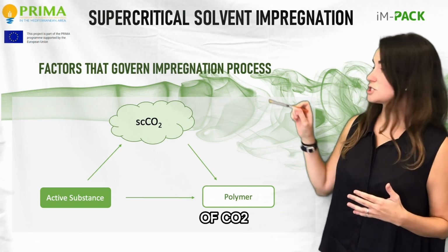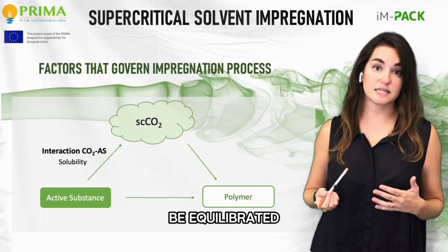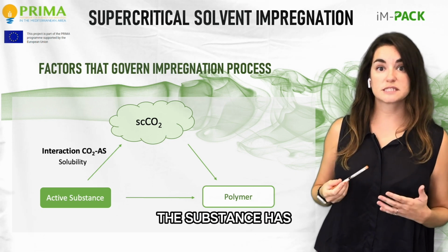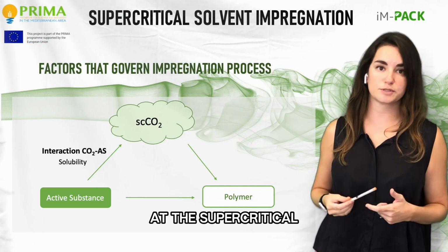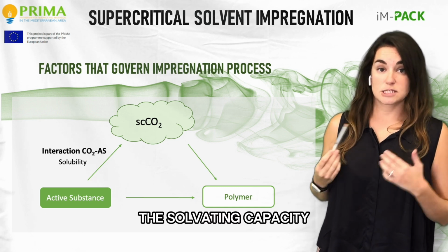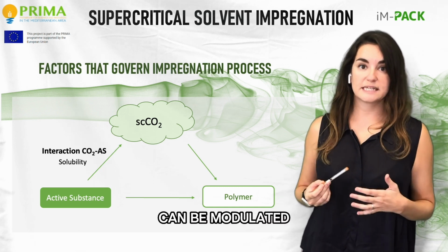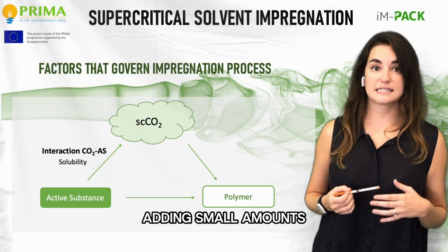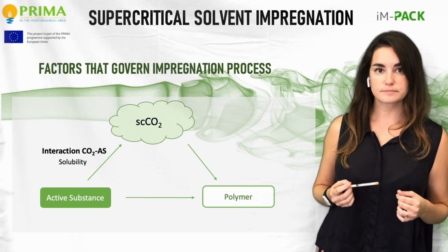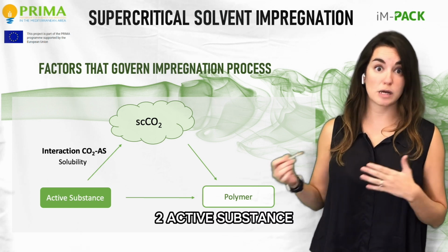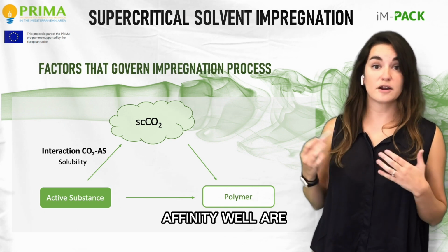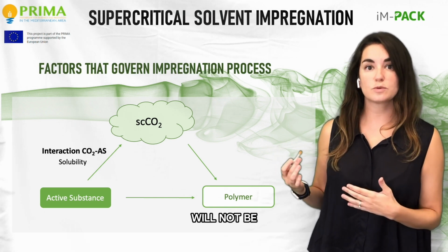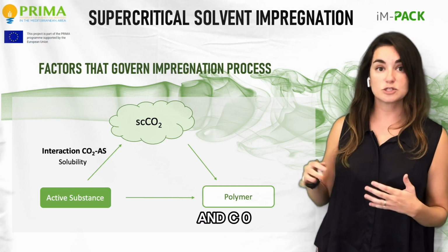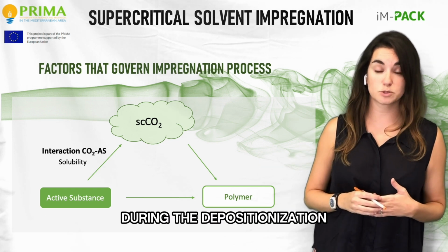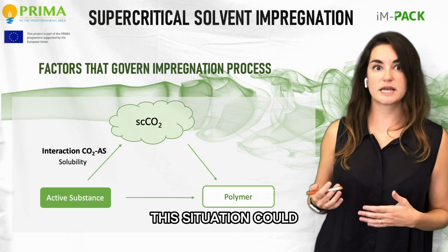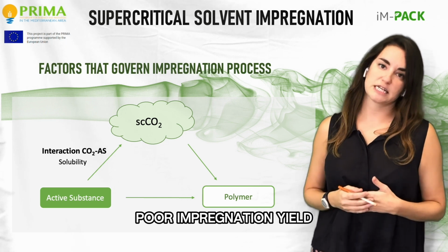First, the interaction CO2 active substance must be adequate. To do so, the substance has to be well solubilized at the supercritical conditions. The solvating capacity of CO2 can be modulated by pressure and temperature, and also by adding small amounts of polar solvents. However, if CO2 active substance affinity is very high, then the partition coefficient will not be in favor of the polymer, and CO2 will drag the active substance during the depressurization phase. This situation could lead to a poor impregnation yield.